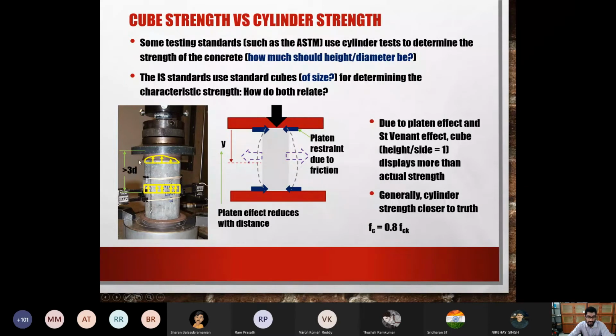This is known as the Saint-Venant effect, where if you go greater than 3 times the diameter, only then will you have uniform stress distribution. Neither is this the case, and also you have this friction. Because of that, cylinder strength will actually be lesser than your cube strength, about 0.8 times your cube strength.